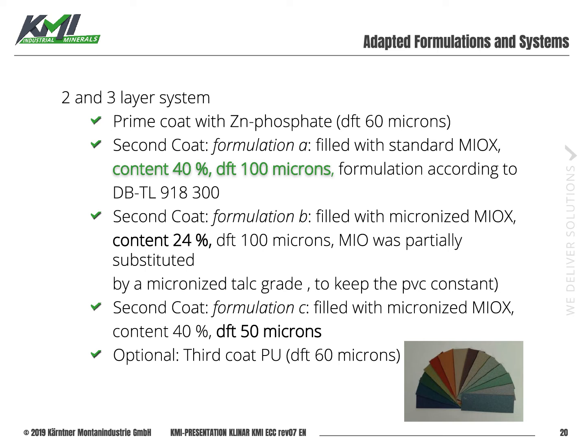The formulation again followed the DBTL guideline. Then we had a formulation B where we replaced the standard grade with micronized grades, but with a loading level of only 24% instead of 40% with the same dry film thickness of 100 microns, and the missing MIO was partially substituted by a micronized talc grade to keep the PVC constant. And we had a formulation C where we filled with micronized micaceous iron oxide at the same loading level, so that means 40%, but we cut back the dry film thickness from 100 microns down to 50 microns.